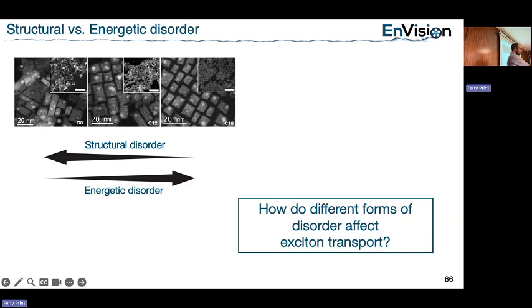No, but we have. I don't have them here. We have a whole set of Brownian dynamics simulations with different distributions, where you really have to first of all deviate from a straight line. Only taking structural disorder into account, you really need to go to fractal-like distributions. It's very difficult to actually get something that is not normal diffusion if you don't take into account energetic disorder.